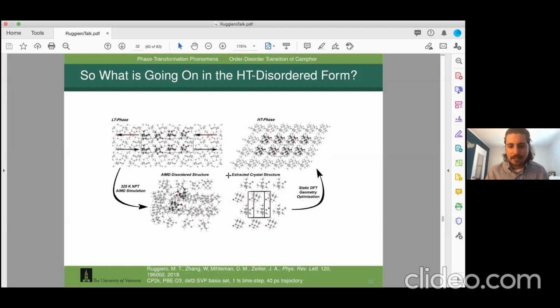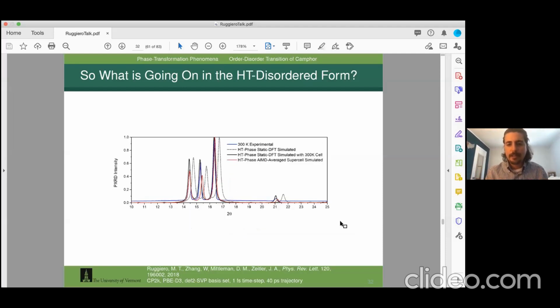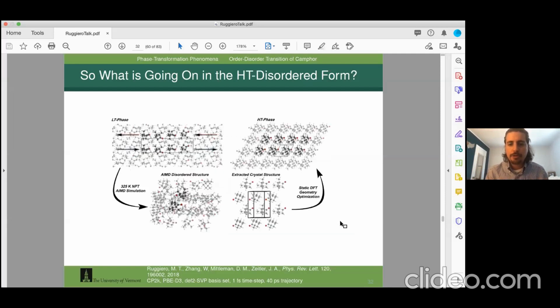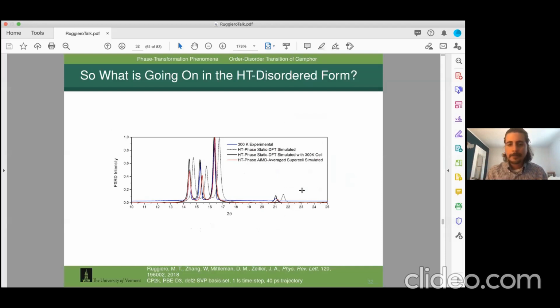If I just take this extracted crystal structure without doing anything, and then do a solid state DFT optimization to get to this kind of structure, that would represent an ordered 0 Kelvin structure, since I'm using static density functional theory to optimize it. What you see if I do that is this dotted line. I get the 3 or 4 features, but they don't line up with my experimental result.